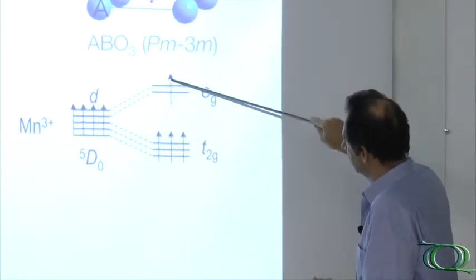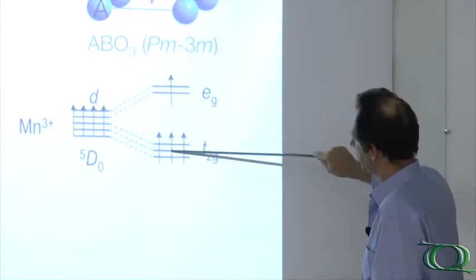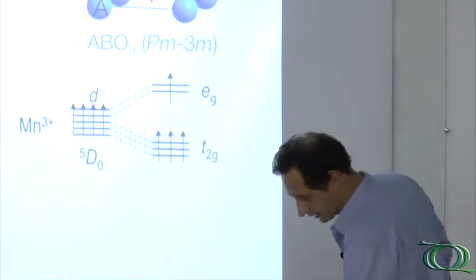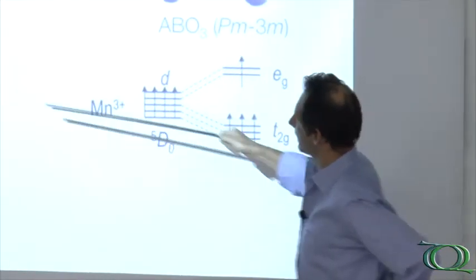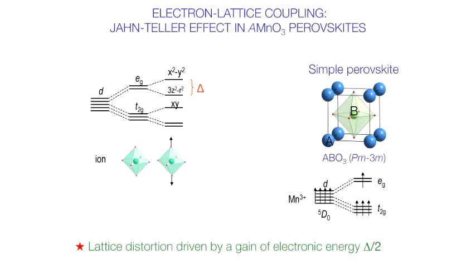The electron here prefers to be here rather than here. So you have to pay this price. But you can pay a lower price if the octahedron is elongated, typically. And in this case, the doublet, the degeneracy is lifted, and this level is now at lower level.